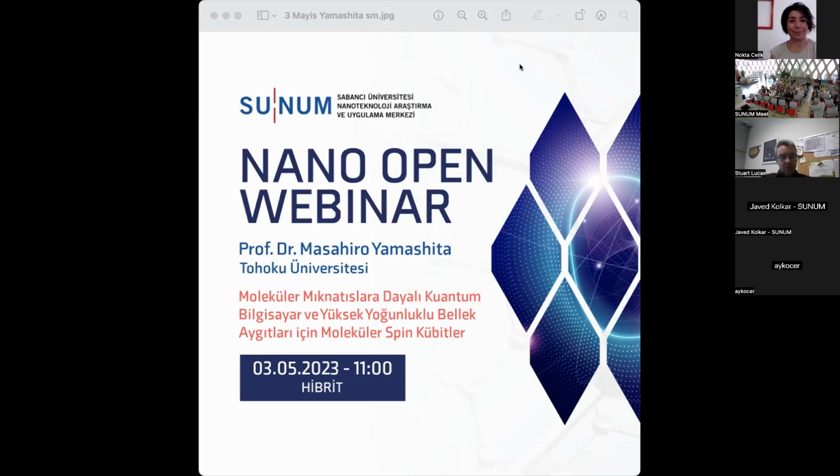But if at the ground state spin flip quantum tunneling occurs, the blocking temperature is very low. So we must suppress the quantum tunneling at the ground state, first sublevel, or second sublevel, leaving only thermal relaxation. Then we must make the energy gap larger. If so, we can realize it. I'm an optimist.